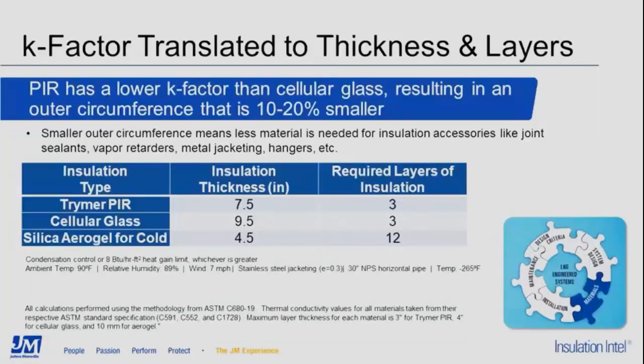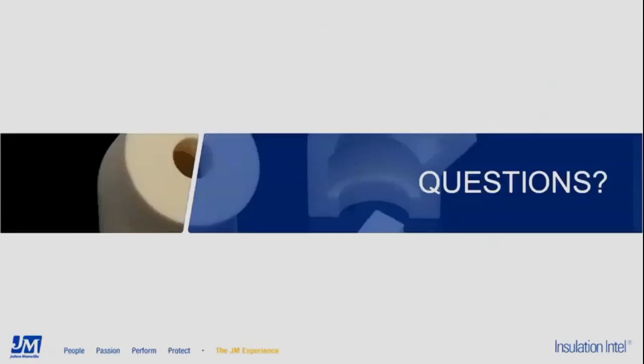Okay, the first thing to realize is that carbon steel pipes can only be used down to a certain temperature. I'm sure that the metallurgists know why, I do not, but carbon steel pipe is used only down to maybe minus 40, minus 50 degrees F. Below that, carbon steel will embrittle. So in LNG applications, you would never use carbon steel pipes.